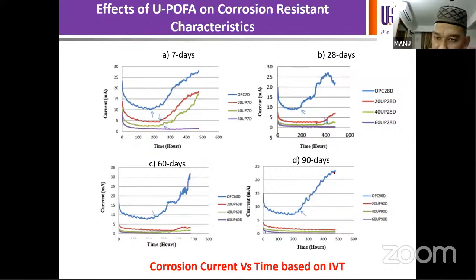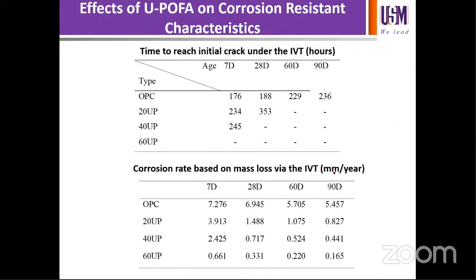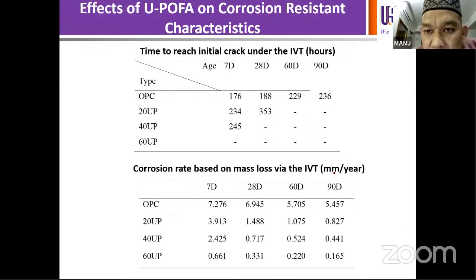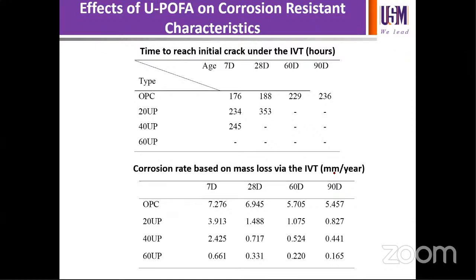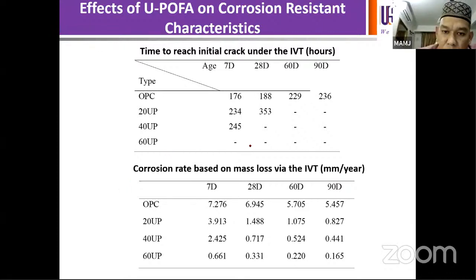All right. So we can expect that if you use this material, it has the potential to provide better protection to protect the reinforcement within our concrete structure. Okay? And here it's giving the time to reach initial crack under IVT test in hours. Okay, so for the 60% UPOFA, based on the limitation of the test, there was no crack observed. All right, but in the 40%, crack was observed at 7 days only, but at longer curing period, no cracks were observed. In the case of OPC concrete, in all samples subjected to 7, 28, 60, and 90 days,